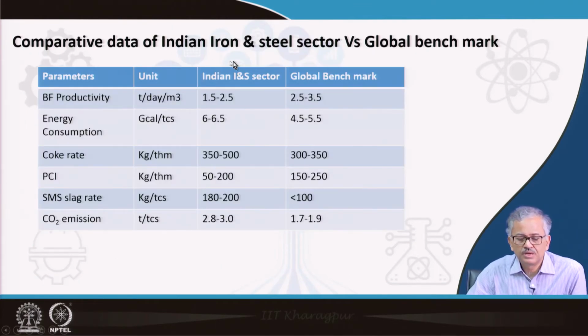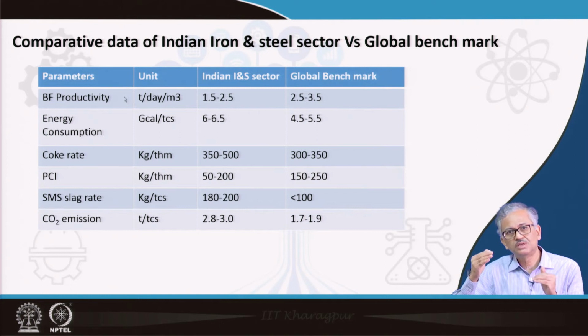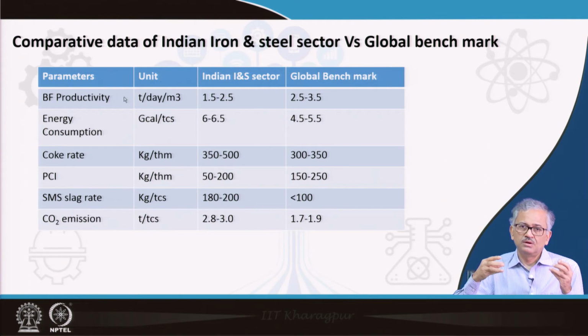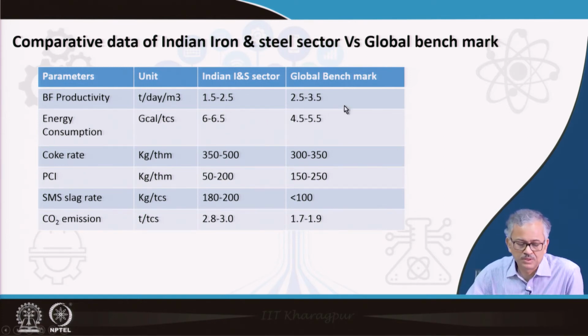Some comparative data of the Indian iron and steel sector versus the global benchmark. If you see productivity, blast furnace productivity in terms of tons per day per cubic meter, India is 1.5 to 2.5 compared to the global benchmark of 2.5 to 3.5. So, Indian production is quite less, we can improve it, and also sometimes we run under production. Whatever the capacity, we cannot produce that much because of lack of demand or some other issues involved in the plants. So, most of the time our plants run under capacity. That is another major problem. Also, productivity is quite low compared to the global benchmark.